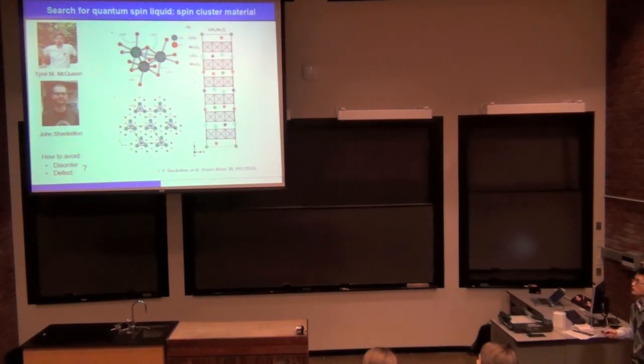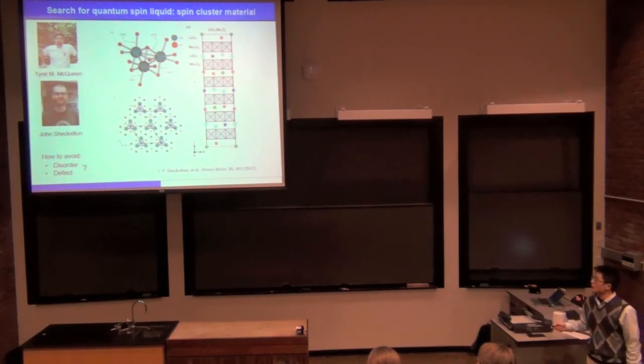And if you do a simple electron count, you would realize that over a single triangular cluster, there are a total of 7 electrons. And 6 of them would be distributed along this triangle in the metal bonds. And so as a result, there's only one single electron shared by a cluster. So each cluster actually behaves like a spin 1/2 particle, and as you look at the magnetic plane, which is here, these clusters form a triangular lattice. So if you think about it, it's a triangle of triangle. And this way, some of the disorder and defect effects can be minimized.